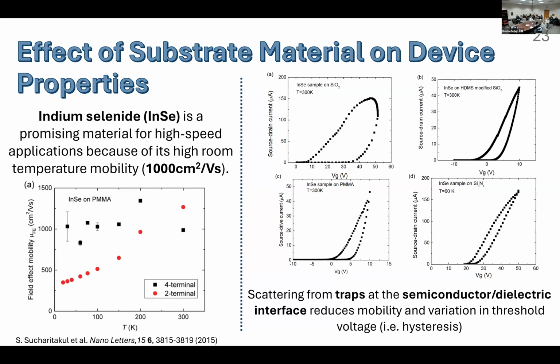As you can see here, depending on what is underneath the indium selenide, whether that is silicon oxide, surface modified silicon oxide, a polymer PMMA, or silicon nitride, that will change not only the mobility, like we said, the slope of this nonlinear regime, it will also change the device stability. So this change in the threshold voltage is what we call hysteresis, and it's not really something that we want to see.